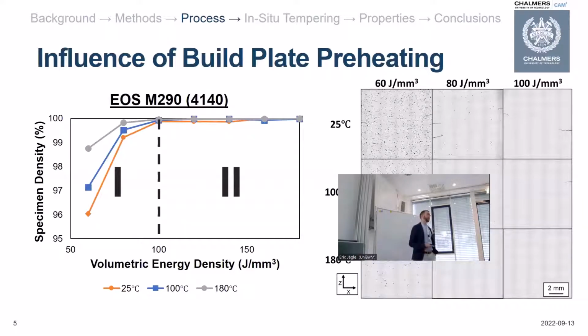The porosity within your specimen was also influenced by the build plate preheating temperature you had. Specifically, it affected the formation of lack of fusion pores when you had low energy input. So in this case, for the 4140 alloy that we had, as you increase your preheating temperature from 25 to 180, you're having a reduction in lack of fusion porosity of about 2-3%. And you can also see that from the cross sections here: as you increase your preheating temperature, the size and number of your lack of fusion pores decrease.